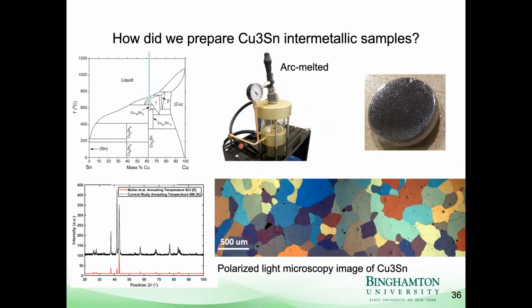So we did this, and then we did XRD, and we could confirm that we have pure Cu3Sn. This is a polarized light microscopy image, and because the optical properties of the metal are different in the different orientations, this microscopy image shows the different crystal grains as different colors.